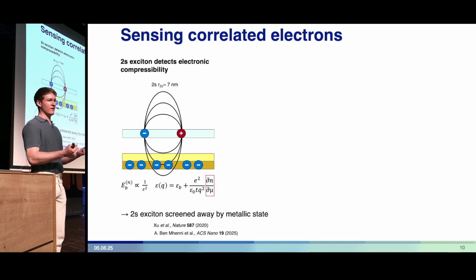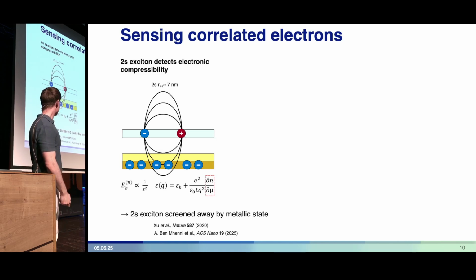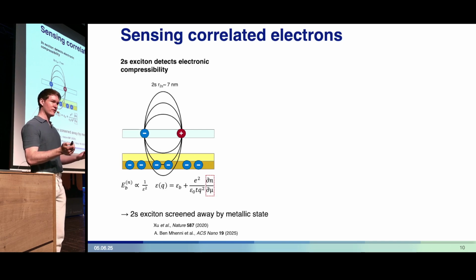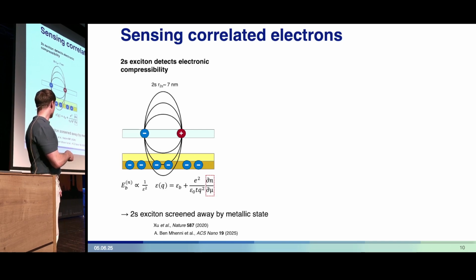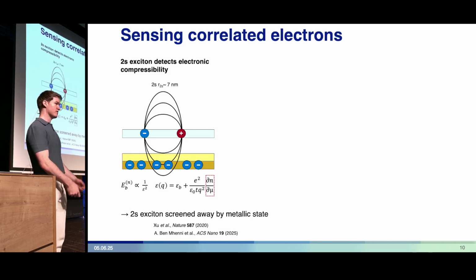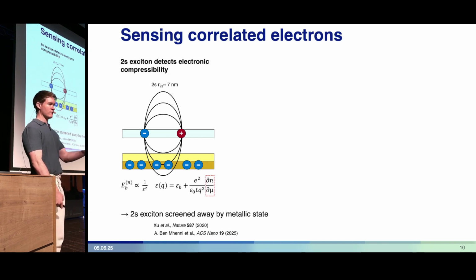This means it's very sensitive to screening by charges that reside within the volume of the exciton, some extended region inside and outside of that layer. More specifically, what it's detecting is changes in the dielectric screening caused by changes in compressibility, which you can understand from Thomas-Fermi screening. So the 2s exciton is a sensor for electronic compressibility.